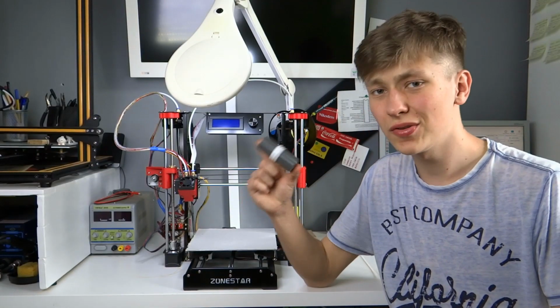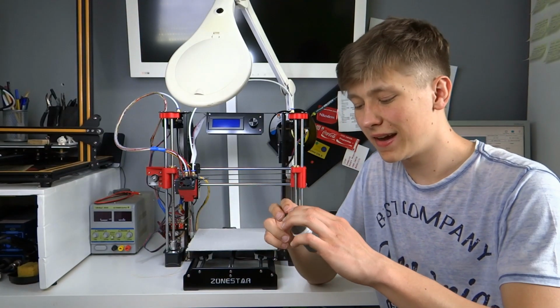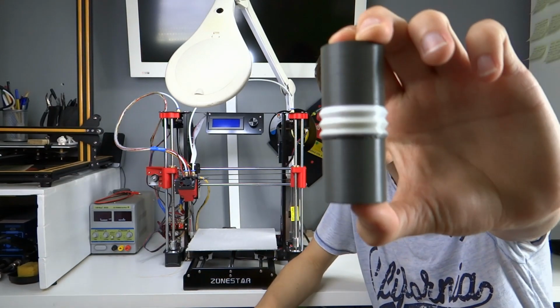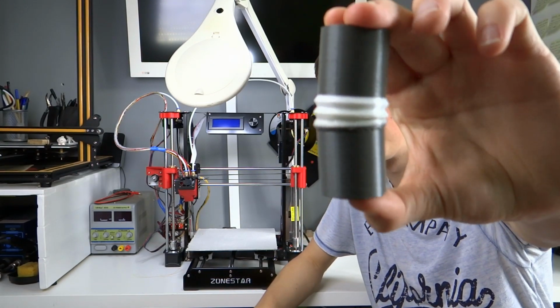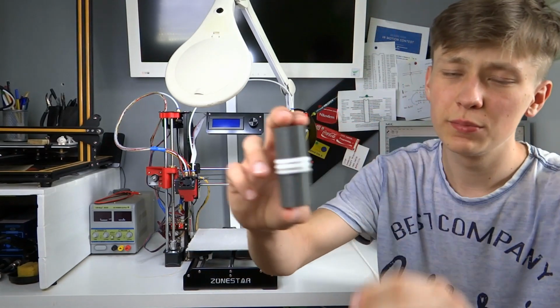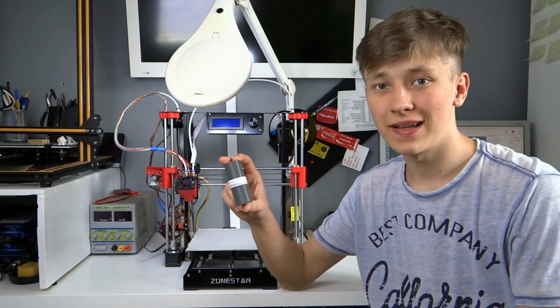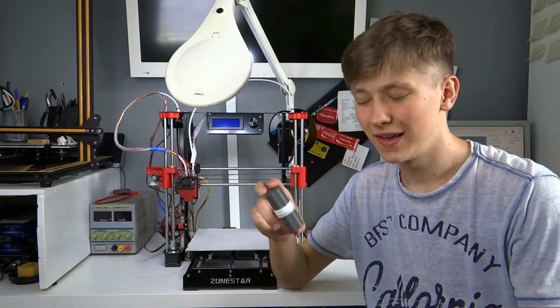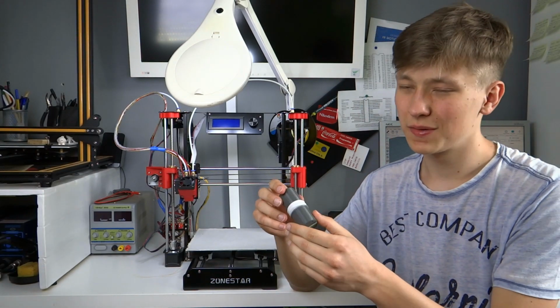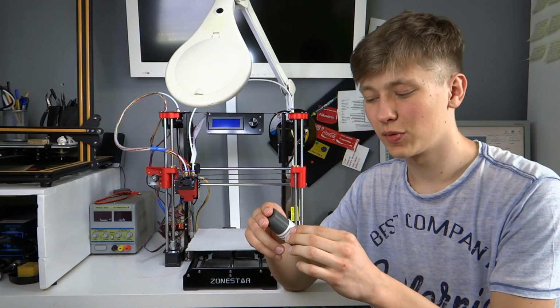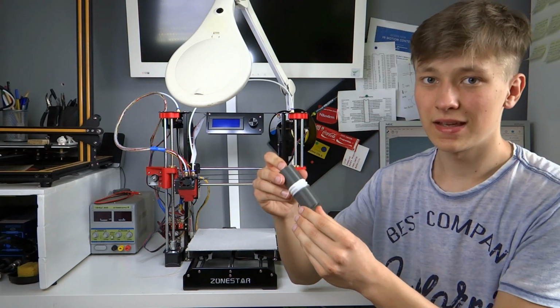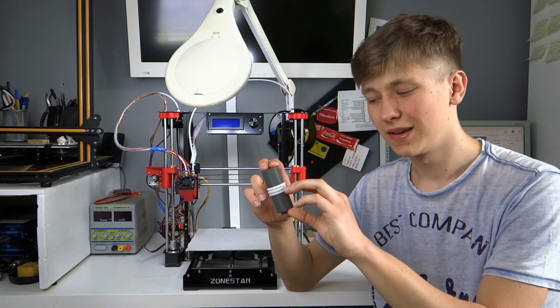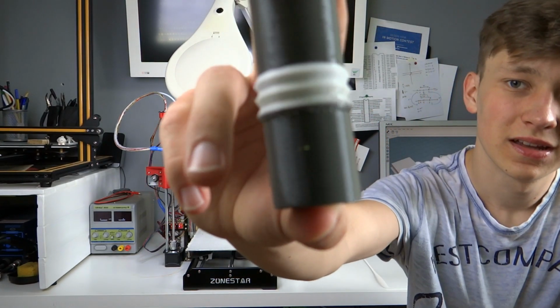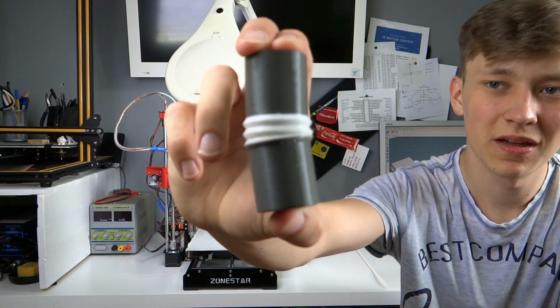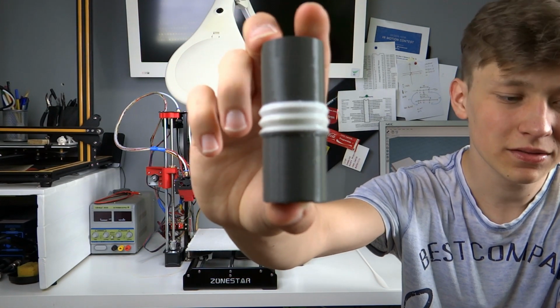But I decided not to stop there. And I tried to connect PLA with TPU, with flexible filament, to check if it will be possible to print like that. And it is. I mean, it's not perfect, because probably the temperature was a little bit too low, and adhesion between layers is not perfect. As you can see, there are some holes between the PLA and TPU filament.